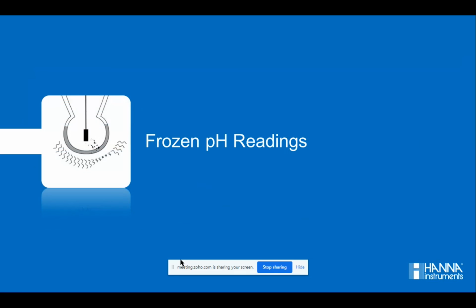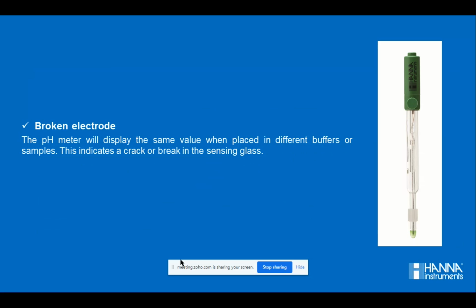Then, if you observe frozen readings. Frozen readings means you observe a particular reading like 6.47 or 5.8 or 7.0 or 7.89 in any of the buffers. It might be 6.1, 6.8, or 7.0 or 4.0 and 12.45. If you have a similar or frozen reading in all the buffers and all the samples, then there is a possibility that your internal electrode is broken internally. Yes, it is possible to have a crack or a break in the sensing glass, thus giving frozen or similar readings in all the samples. This is the time that you have to replace your electrode with a new one.